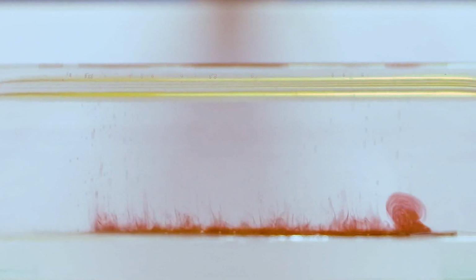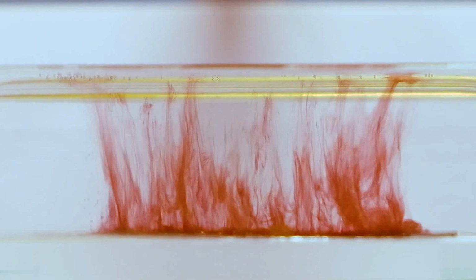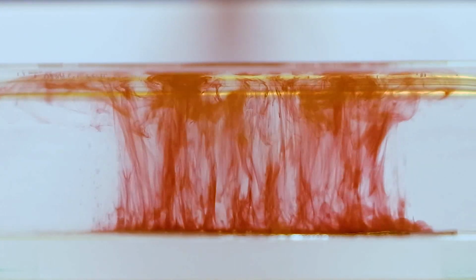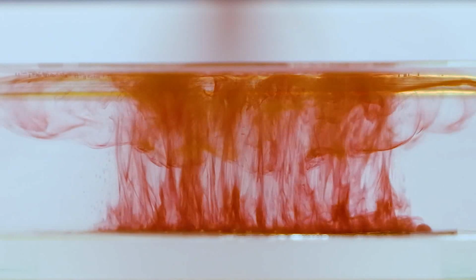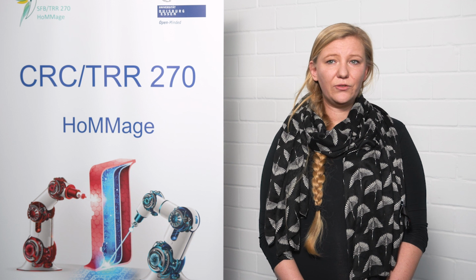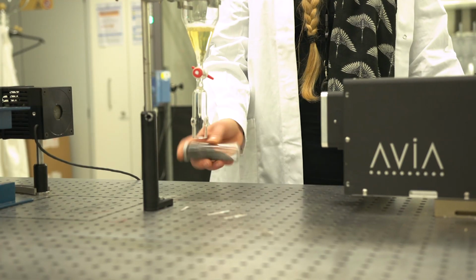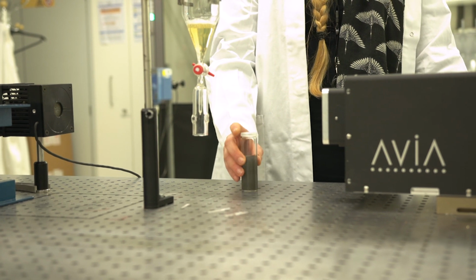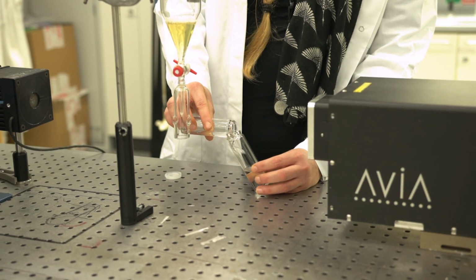Here, additive manufacturing is a promising approach as it allows the production of complex structures under low waste conditions, minimizing the need for rare earth elements. Printing permanent magnets, however, is challenging as melting and solidification critically affect the macroscopic and microscopic properties of permanent magnets. A11 addresses exactly this issue and adds nanoparticles to the surface of the magnetic micropowder to sufficiently influence even the melting and solidification behavior. We produce our nanoparticles surfactant-free in water using high-power, ultra-short pulse laser systems.